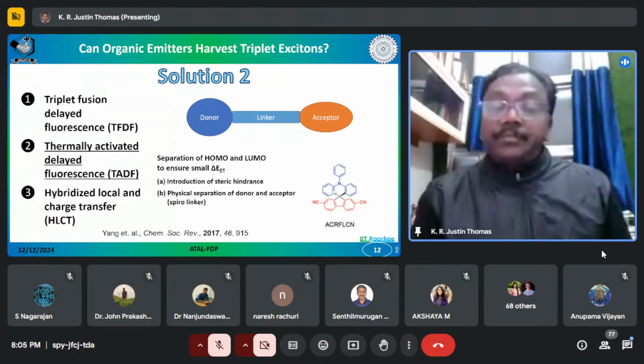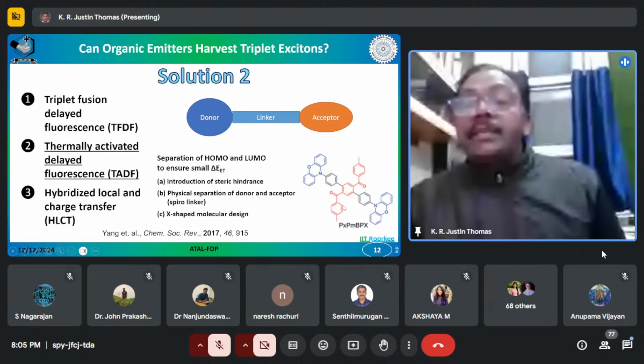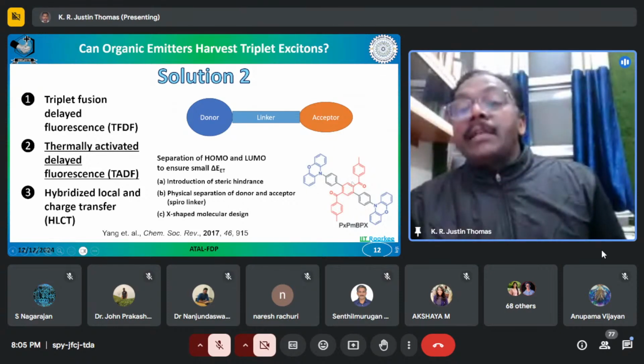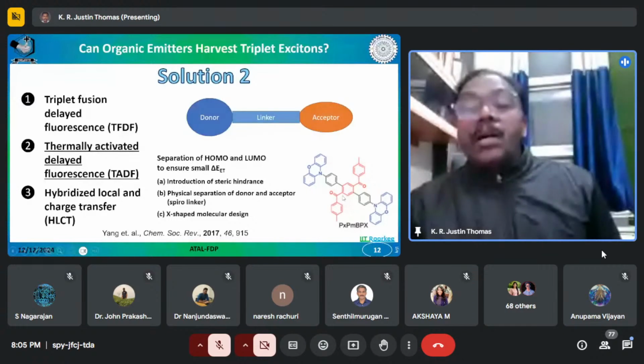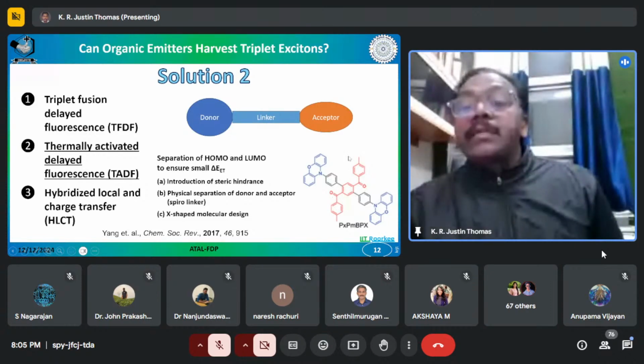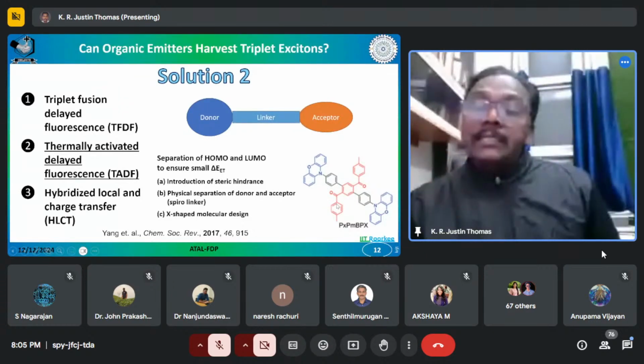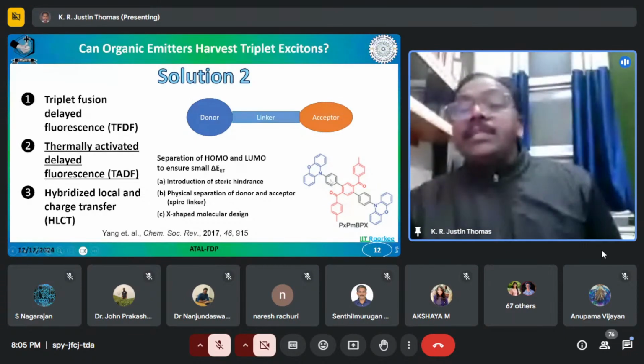That is cross-conjugation. As I have shown here, if you have a tetra-substituted benzene derivative in which the donor moieties are para to one another, and the acceptor moieties are para to one another but ortho to the donor, this is the cross-conjugated molecule. Now one acceptor unit will be conjugated effectively with the other acceptor unit because they have para orientation, but they will have a poor interaction with the donor because it is ortho to the acceptor. So the conjugation axes are perpendicular to one another,